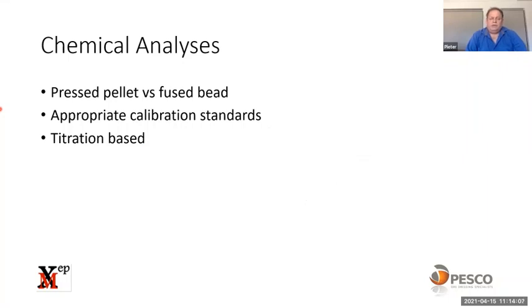Chemical analysis that we use, as I just spoke now, is XRF. But when you use XRF, there are also different methods of analyzing. Use a press pellet versus a fuse bead, or even some mines like to use a titration for Fe or manganese. It's very important when you do press pellet and fuse bead that you understand there are certain accuracy impacts on your XRF. With a press pellet, your calibration is critical. You must make sure that you've got the right calibration for your type of mineral, your type of matrix. The moment you use fuse bead, that matrix is destroyed, and you have a much more accurate analysis.